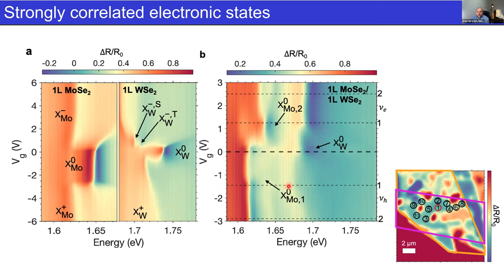The first thing we can say is that we have the expected behavior of the type two band alignment. So with doping into the molybdenum diselenide conduction band or into the valence band of the tungsten diselenide, we suppress the neutral A exciton and we create charged excitons. And that's why, for instance, the oscillator strength goes very, very small for p-doping in the tungsten diselenide, or for n-doping in the molybdenum diselenide. And in addition, we can see that there's some clear modulations in the energy and intensity at specific gate biases. You can see here I've labeled this one hole per site, and I'll explain why we name that later.